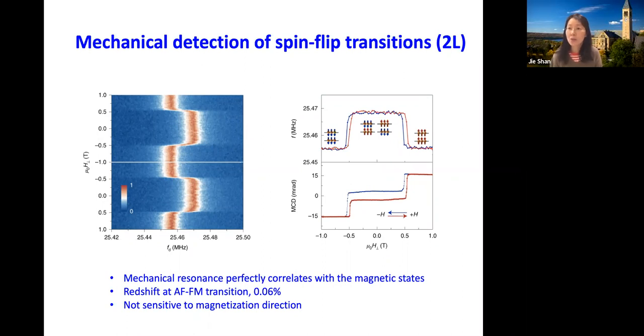The other thing I want to point out is that, in the MH curve, we have negative and positive magnetization. In the mechanical resonance frequency, we don't see any difference.